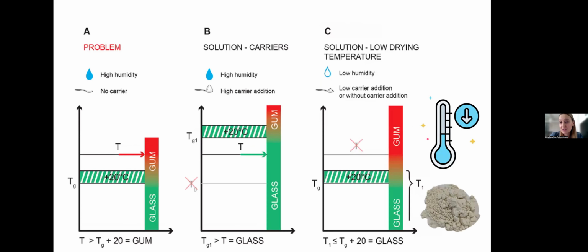So what is our solution? What we are working with is lowering drying air temperature. When we lower drying air humidity, it is possible to lower drying temperature. So we are ensuring that we are not reaching this point where we can observe the stickiness. At the same time, we can lower the carrier content or even eliminate it completely, because it is not necessary right now if we are lowering the drying temperature, because we are moving this point a bit lower.